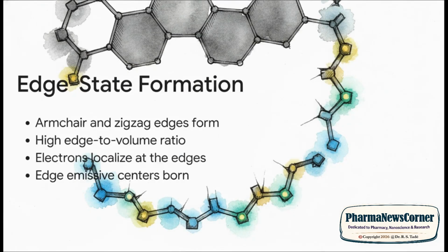Now, what's really fascinating is what happens at the physical borders of our newly minted quantum dot. When we fragmented that large sheet, we didn't just make it smaller, we created massive amounts of new edges, specifically what chemists define as armchair and zigzag edges. Because the dot is so tiny, it has a phenomenally high edge-to-volume ratio. And those pi electrons that used to roam free across the bulk sheet, well, many of them become trapped. They get localized right at these zigzag and armchair boundaries. These trapped electrons form our very first edge-emissive centers, acting as localized electronic states that actively participate in fluorescence.